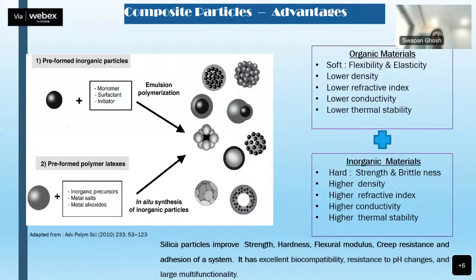In a reactor, you can synthesize the silicon oxide particles, and in the same reactor, you continue the further polymerization reaction. So when it is a preformed particle, then monomer, initiator and surfactant are all added, and then polymerization is conducted, and we can have a composite particle where silicon oxide is coated by a polymeric material.